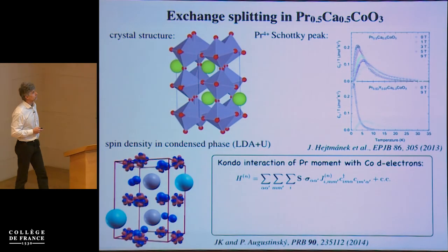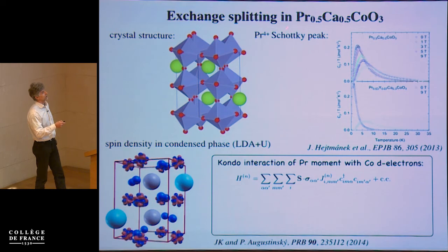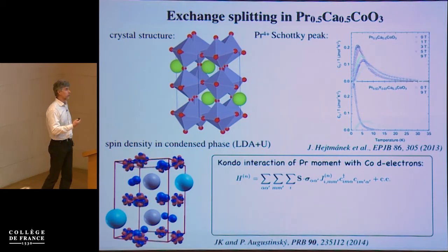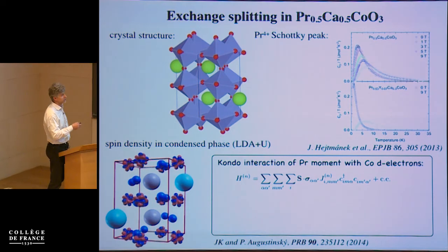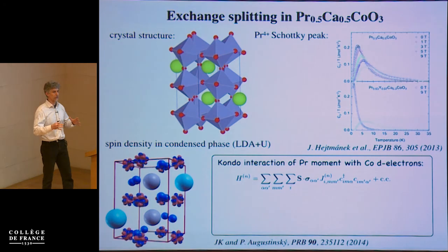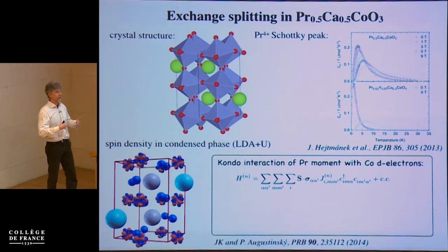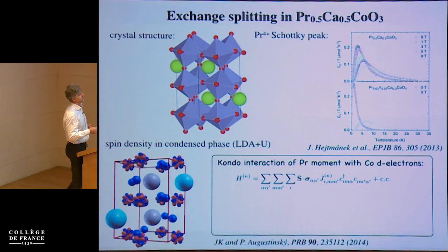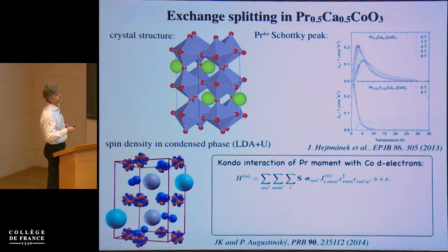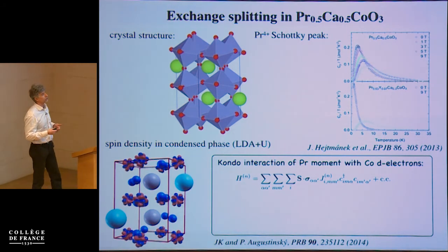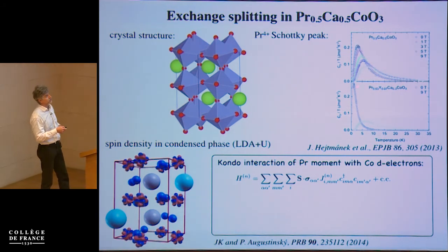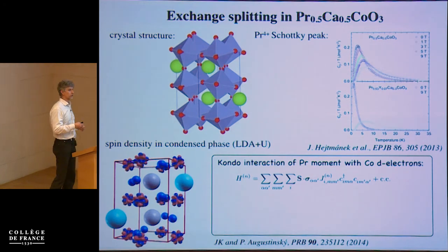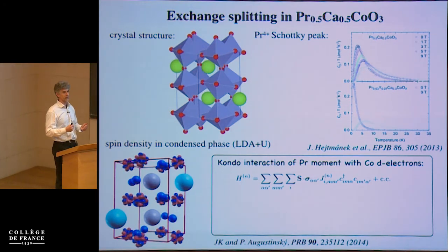Now, this calcium praseodymium cobaltate is a material where there is a real phase transition observed, and I told you a little bit about it at the beginning, but I didn't tell you, from my point of view, the most interesting fact: that the ordered phase breaks the time reversal symmetry.